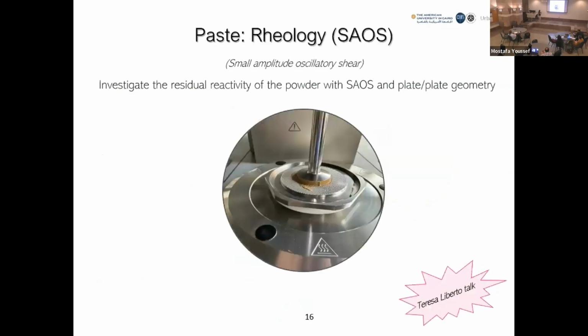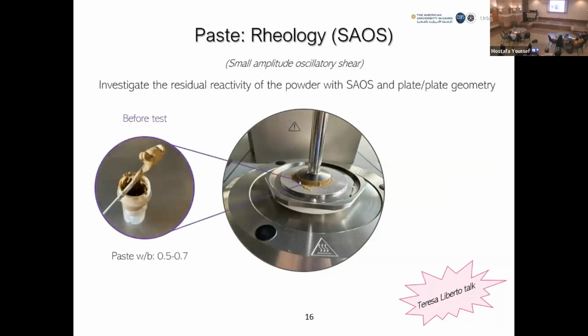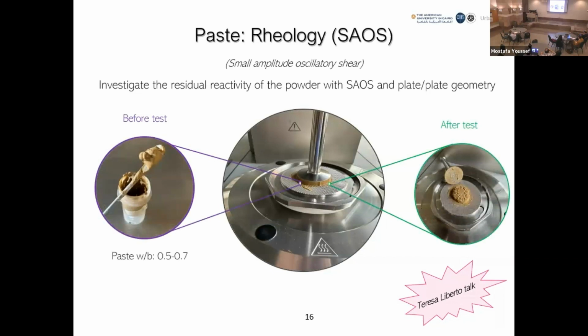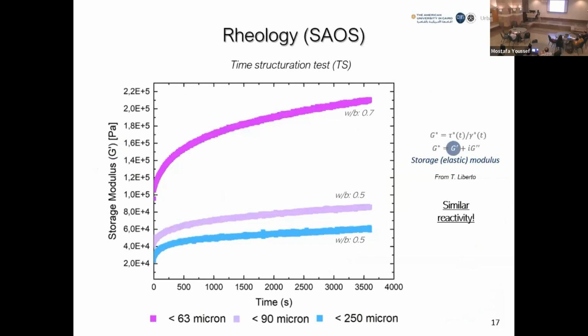And in this case, rheology, and in particular SAOS, helped me a lot. I don't want to talk a lot about this because my supervisor, Teresa Liberto, already did yesterday, but just to give you some information, what I did with rheology is just to create different pastes with different granulometric sizes and analyze the residual activity. To analyze the residual activity, I did a time structuration test, and the residual activity is represented by the slope of all of these three curves.